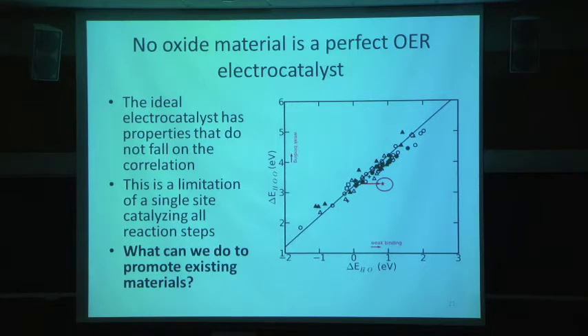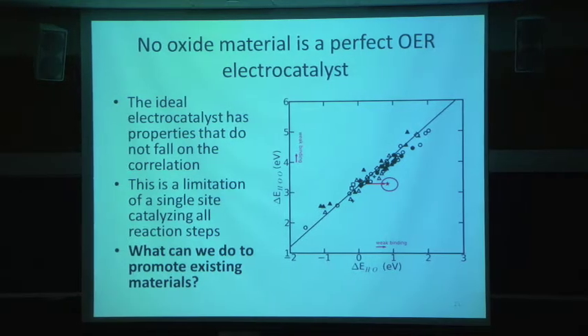Even more, because of the correlations that we showed, it suggests there's not a material that is catalyzing all the reaction steps by a single site, which is what happens on most metal oxides. So now what could we do to think about promoting existing materials? If we postulate that there is a fundamental wall that you can't exceed, then we should probably focus our efforts somewhere else than trying to beat it. So we can take existing materials and ask, could we mix metal oxides to make them better? Could we make nickel somehow as good as cobalt, or cobalt somehow as good as ruthenium by mixing it with another species?